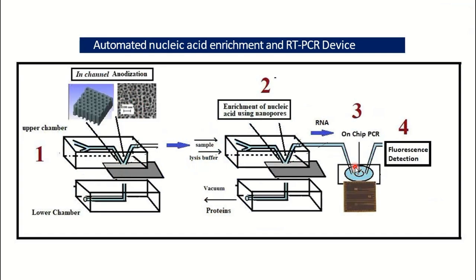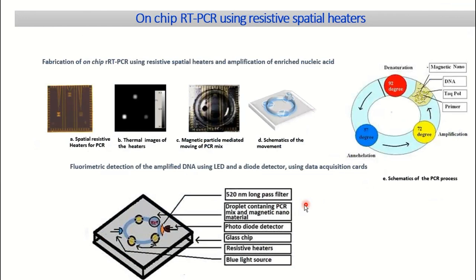Here we have also fabricated an on-chip PCR. So this on-chip PCR is a specialized PCR. In general, PCR takes around 2 hours or 2.5 hours, but in this case the PCR can be done in 20 minutes. The main time required for the PCR is to change the temperature, not the PCR reaction. So here we have designed three PCR temperature zones that can be heated, and the droplet, with the assistance of magnetic nanoparticles, can be moved across these three temperature zones, and the PCR can be done.